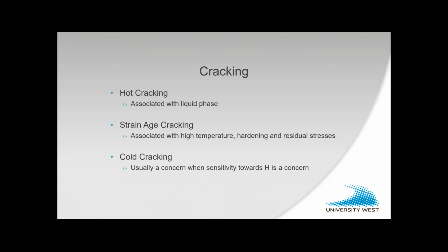So from our research perspective, most of the research projects that we have refer to weldability and specifically to cracking susceptibility. When you deal with cracking susceptibility in the superalloys, it's primarily hot cracking, which could be at stake during welding associated with the liquid phase, as well as strain age cracking. Strain age cracking is also at high temperature, but not necessarily involving the liquid phase. Cold cracking could be a concern, but it's not a big issue with the superalloys. So here today I will show more towards strain age cracking.